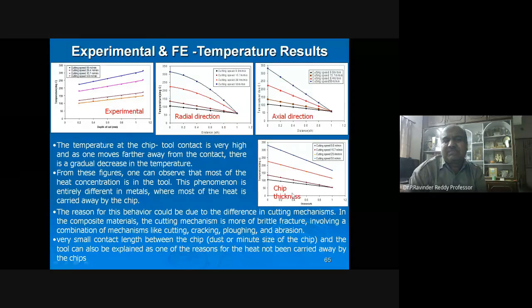The temperature at the chip-tool contact is very high, and as one moves further away from the contact, there is a gradual decrease in the temperature. From these figures, one can observe that most of the heat is concentrated in the tool. This phenomenon is entirely different from metals, where most of the heat is carried out by the chip. The reason for this behavior could be the difference in cutting mechanisms.